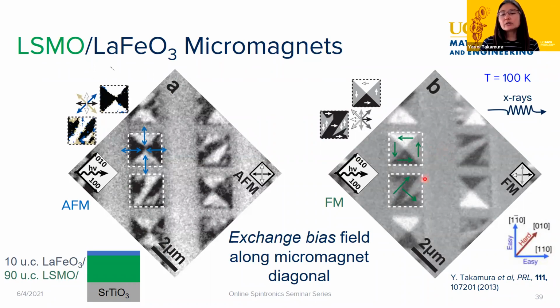And we could also get these kinds of domain structures to arise by, again, having this local field, which we think is an exchange bias field, which wanted to lie along the diagonals, and they would just randomly appear depending on which micromagnet we have. So it's an interesting case where we get both spin flop coupling as well as exchange bias, so both of those types of exchange coupled interactions were occurring in the system.